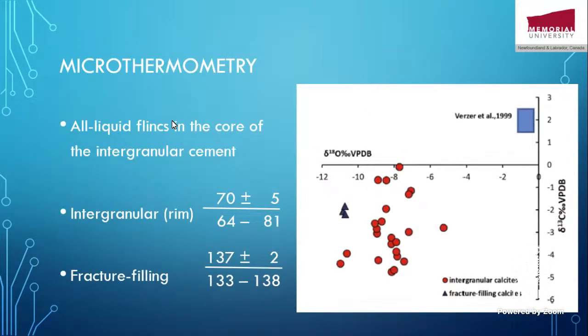When we looked at the microthermometry, we found that there were intergranular cements, and there were all-liquid inclusions in the core of the intergranular cement. This tells us that the cementation started at an early stage of diagenesis, probably at near-surface conditions, temperature less than 60 or less than 50. And the rims of those cements have two-phase fluid inclusions. So the cements grew with progressive burial, and in the rim there were primary two-phase fluid inclusions. The homogenization temperature there was probably around 70 degrees plus or minus 5, varying between 64 and 81. And the fracture-filling cements had a homogenization temperature of about 137 degrees, minimum 133 and maximum 138.